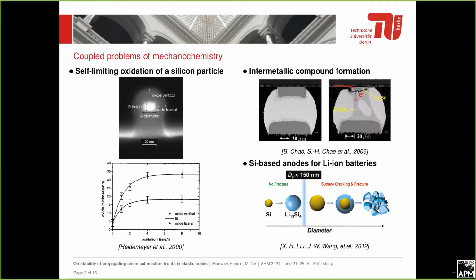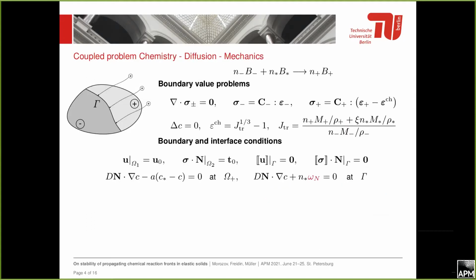found a paper which stated empirically that silicon particles, due to lithiation, depending on the size of the particle, may have some cracks, and of course these cracks are no good for our future lithium-ion battery cell. So trying to understand all these phenomena, we were utilizing the concept which was proposed by Professor Freidin almost 10 years ago.